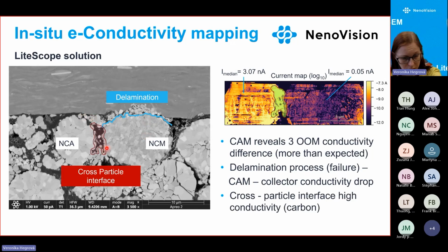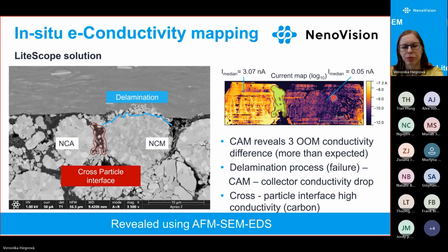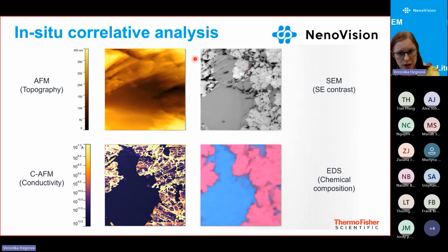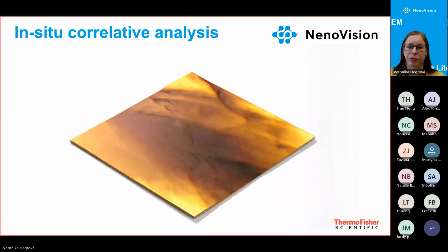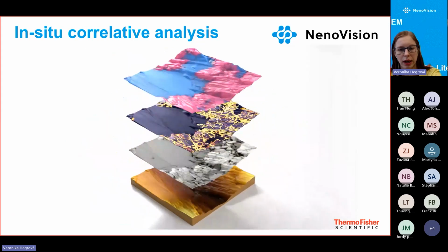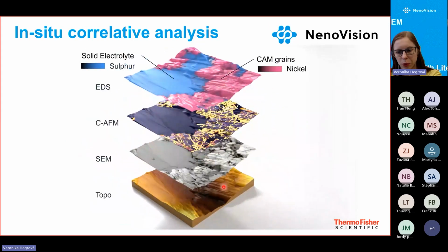If we have a closer look in the EDS, we saw that this cross-particle interface is actually carbon. So the conductivity is flowing in this direction. It still preserves the conductivity of this grain, even though it's not connected with the collector anymore. It was revealed thanks to the combination of AFM, SEM, and EDS. We can correlate the data, so we measured topography, secondary electrons, conductive AFM, EDS. We can put them all together and place one on another and compare what we see and what is likely the reason, for instance, for the failure.